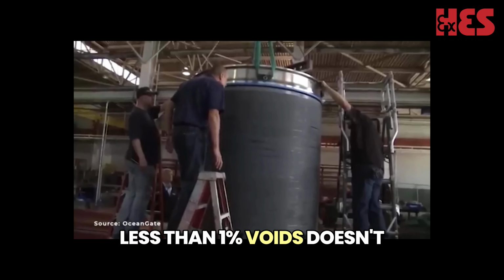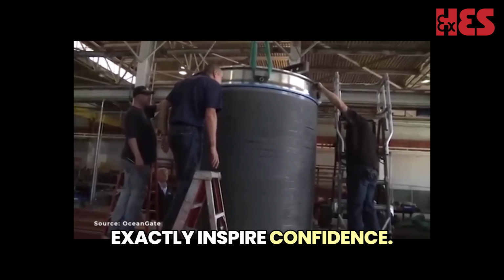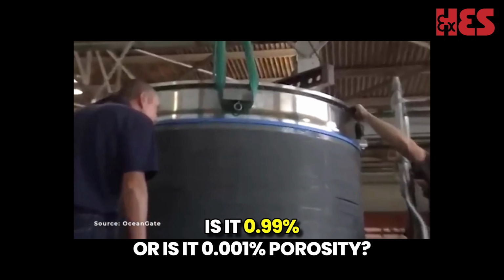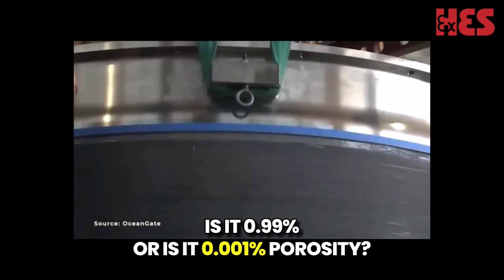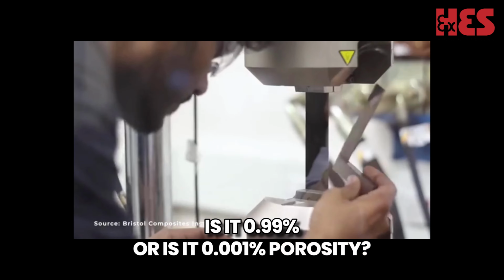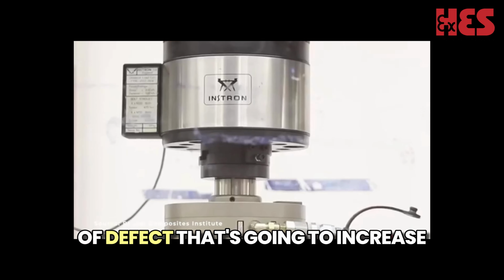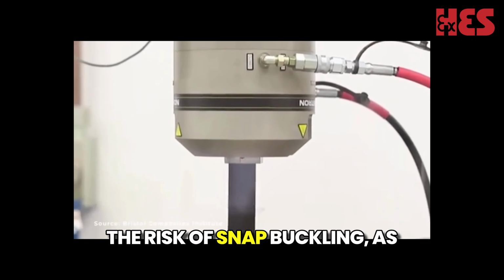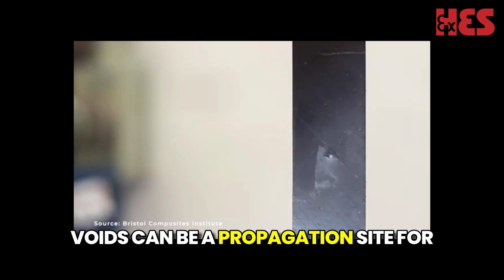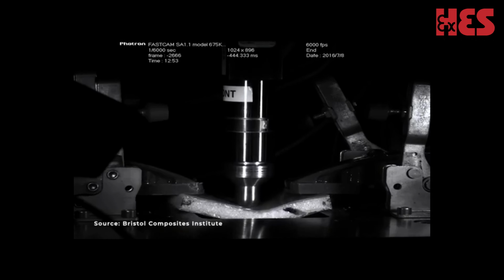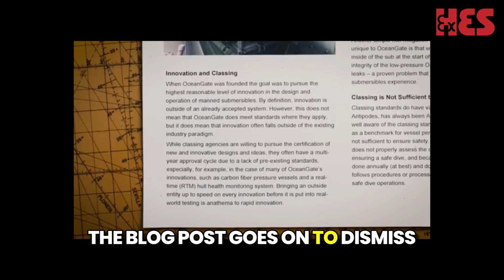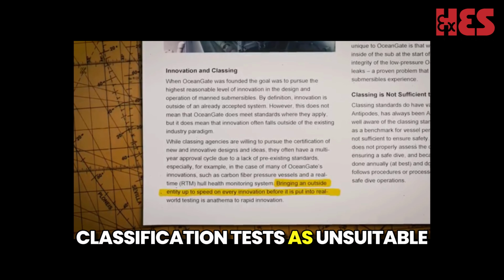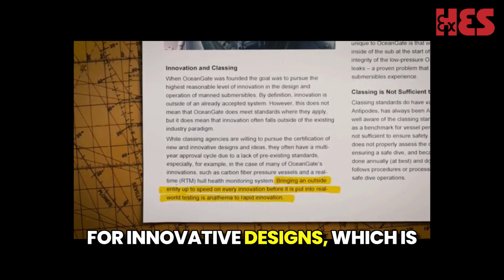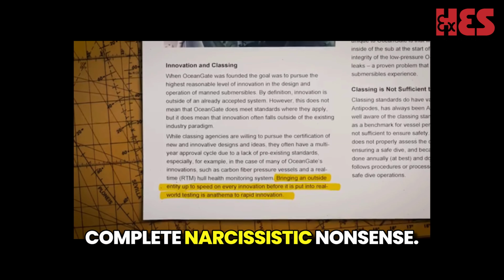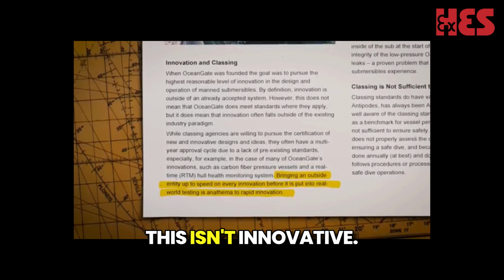Less than 1% voids doesn't exactly inspire confidence. Is it 0.99% or is it 0.001% porosity? That's exactly the type of defect that's going to increase the risk of snap buckling, as voids can be a propagation site for delamination. The blog post goes on to dismiss classification tests as unsuitable for innovative designs, which is complete narcissistic nonsense. This isn't innovative.